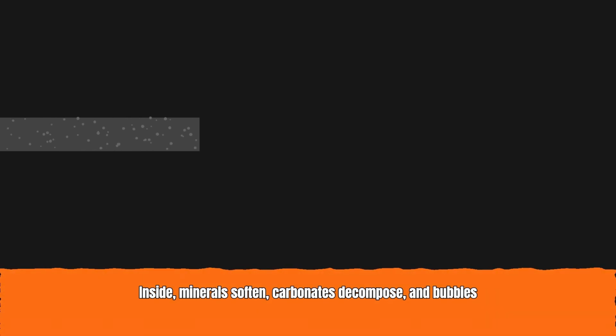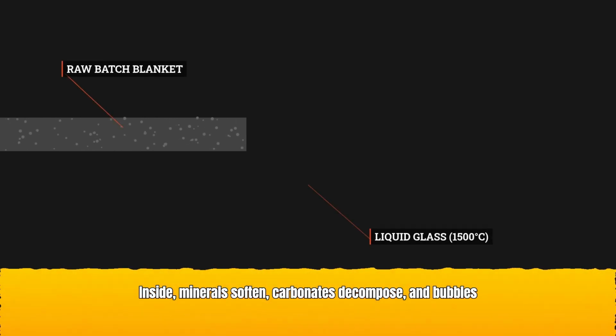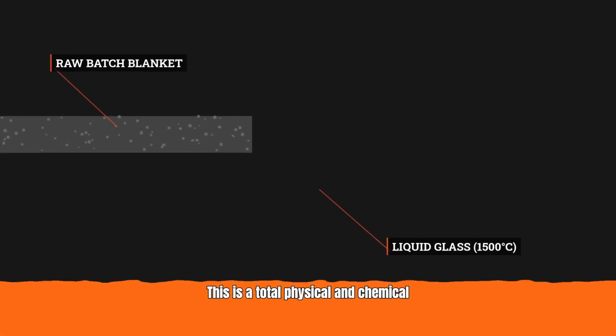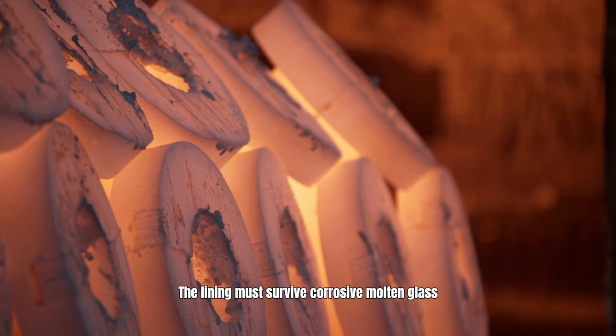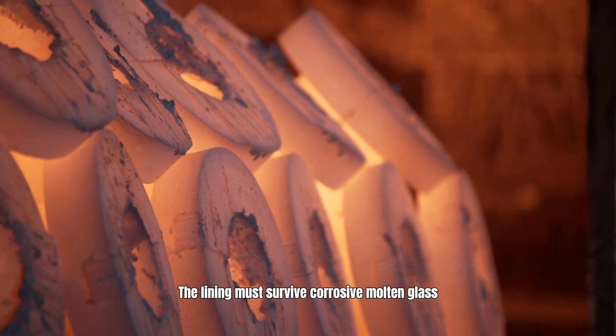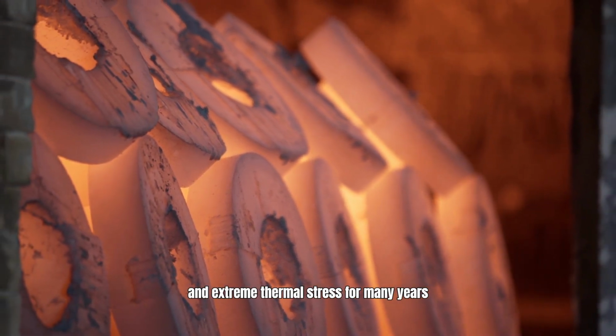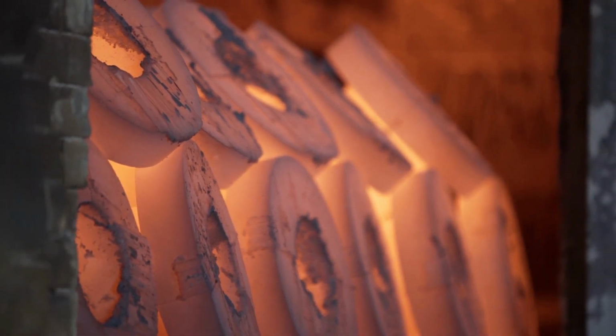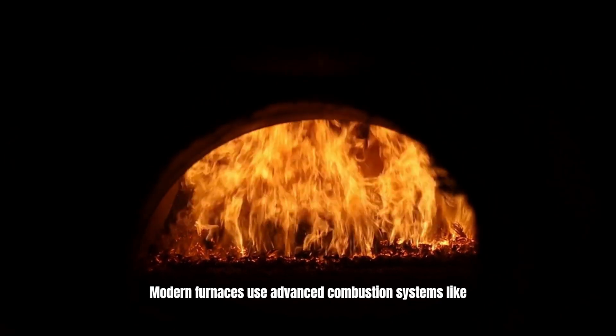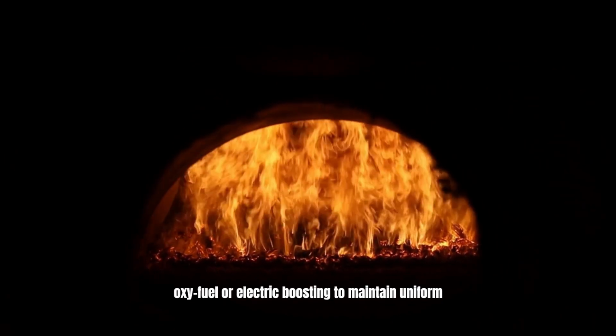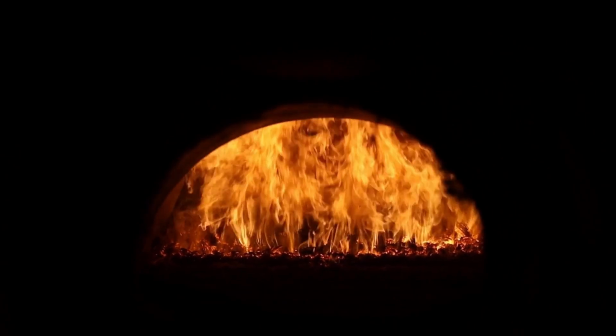Inside, minerals soften, carbonates decompose, and bubbles escape. This is a total physical and chemical transformation. The lining must survive corrosive molten glass and extreme thermal stress for many years without failure. Modern furnaces use advanced combustion systems like oxy-fuel or electric boosting to maintain uniform quality.